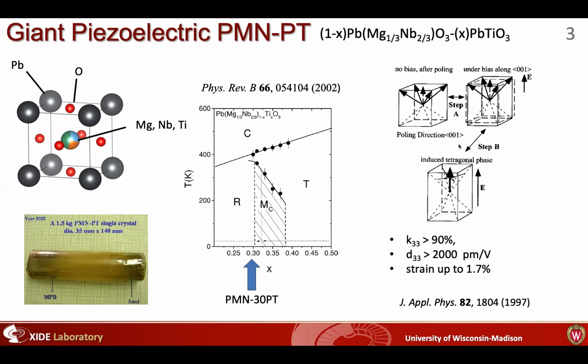One thing I want to highlight, though, is that in the 001 orientation, when you have rhombohedral polarizations and you rotate them towards the tetragonal phase, you really expect only these isotropic in-plane strains. Back when I first started at Wisconsin, we were limited to this 001 orientation, and it was the only orientation we could grow on silicon. That's why, as I'll show in the next couple of slides, we had to use silicon. But just keep in mind that in this 001 orientation, you really only expect isotropic in-plane strains.